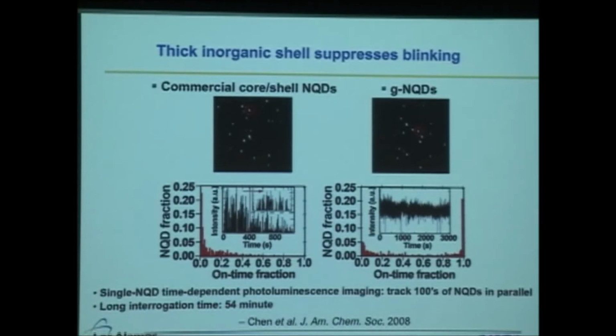They have very, very high efficiencies in terms of ensemble quantum yields. But nevertheless, they exhibit typical blinking behavior. This is a single particle time trace for PL intensity.